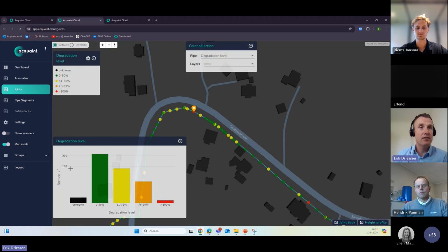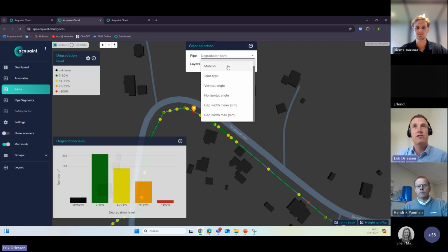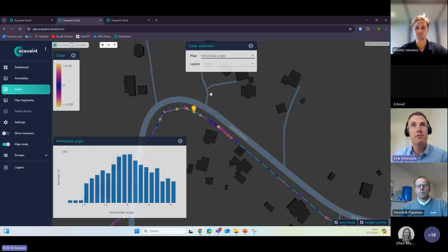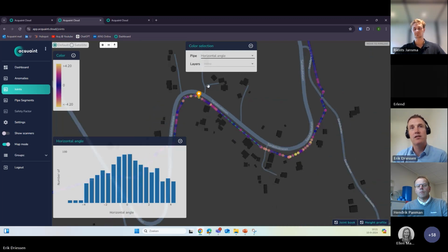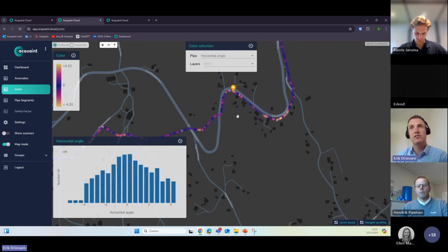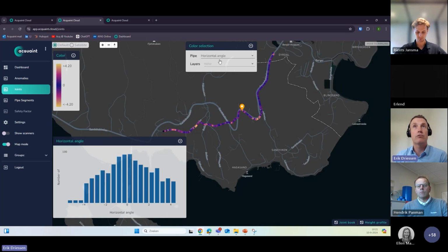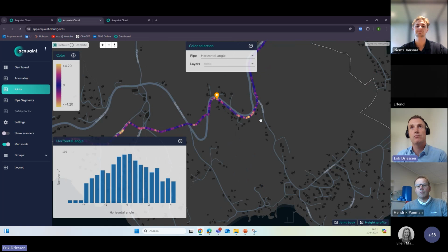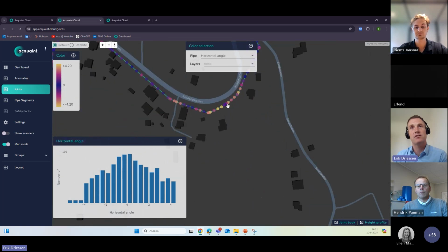So this is a value together, but you can also extract individual measurements. So if you're interested only, for example, in the horizontal angular displacement, the color code changes from -4 to +4 degrees. And you can see that the spread of the horizontal angular displacement is colored differently here. You see more horizontal angular displacement in this curve, for example.